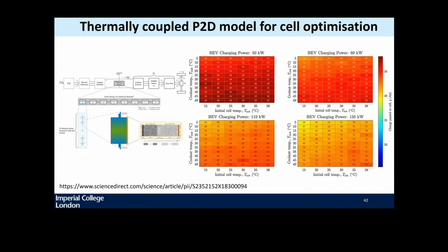So to have a maximum temperature that the cell can reach, after which you cut off performance, is quite normal. That's how you prevent spectacular and devastating failure. And so you want to have temperatures lower than that critical temperature, but also you want to not plate. And in terms of the mechanisms, these are contradicting.